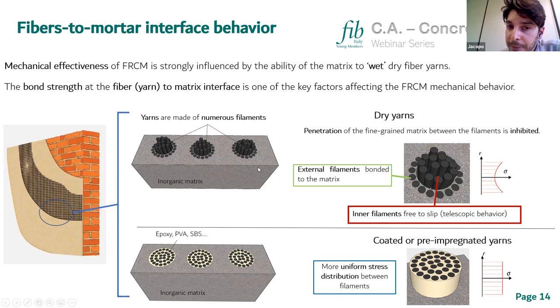These are the two extreme cases. When we have dry fabric, or when we impregnate the fabric with a polymer, which can be epoxy, for example, in this case we have a more uniform stress distribution between the filaments because they cannot slip between each other. And of course, in this case, the adhesion that develops between the coating and the inorganic matrix is very important.